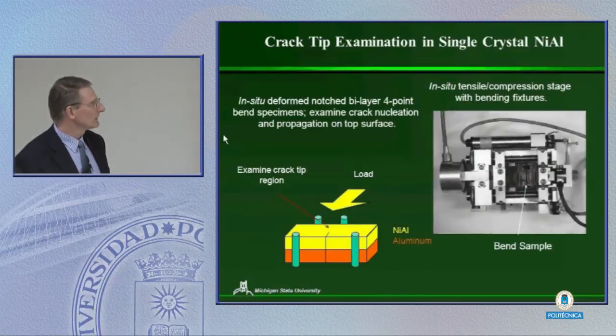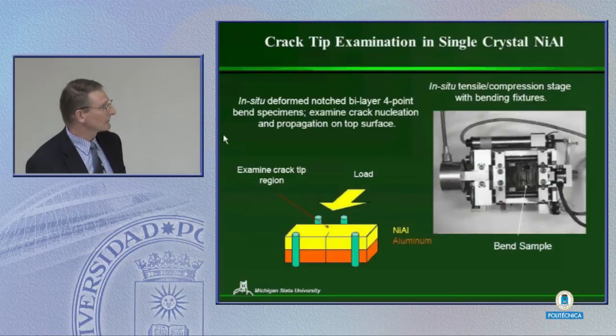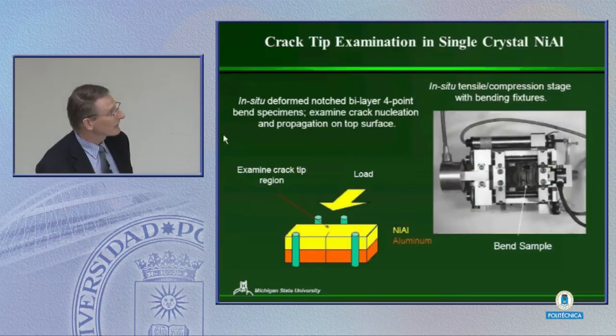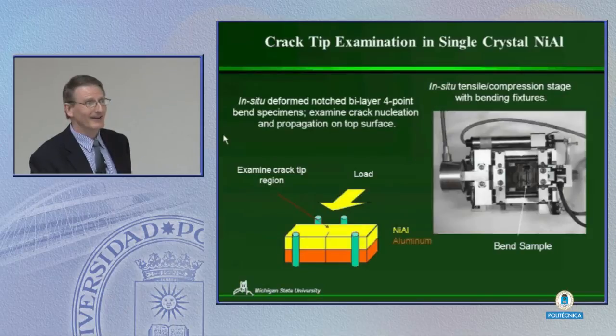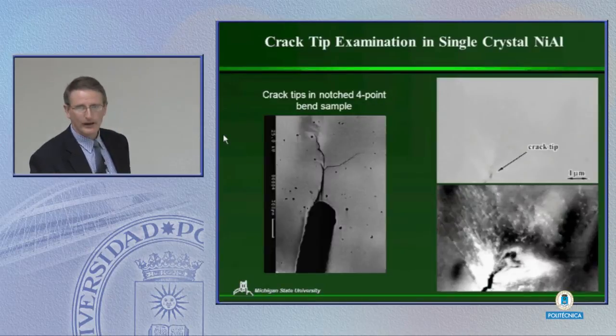And so what we're doing is we're taking a sample like this. The nickel aluminum is still very brittle, so we actually bond it to an aluminum substrate, really just to increase the toughness a little bit. And we take the sample and put it in our deformation stage here, and you can see it right there, maybe. All we're doing then is deforming this, and we're looking at how the crack propagates out of this notch here. This shows you the notch, and you can see how the crack deformed here and actually branched here.